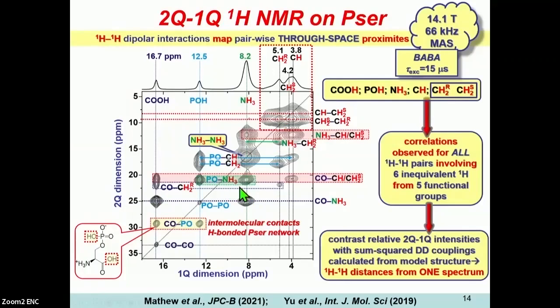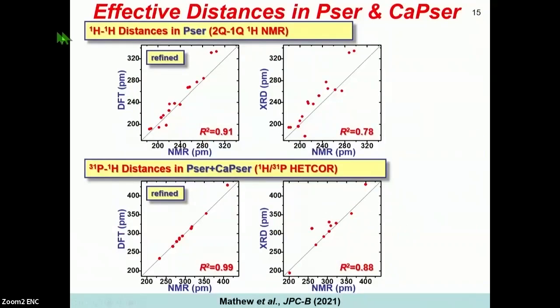structure model that you want to validate. It can be generated from any experiment or modeling, and then you calculate the sum squared dipolar couplings from the model structure, and then you compare it with the experimental data. Here you see some results. We got proton-proton distances from phosphoserine, where you see the NMR-derived effective distances plotted against those from the XRD structure before and after refinement by DFT.